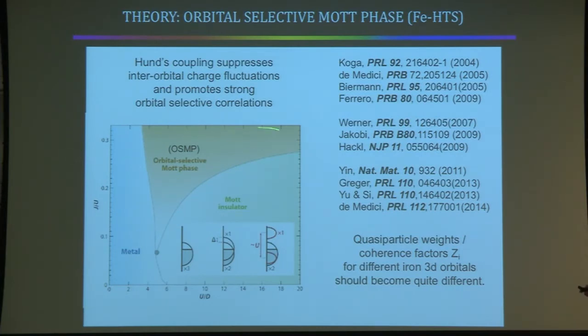That's why this diagram here of orbital selective Mott phases depends on the strength of the Hubbard term on site, but it also depends on the strength of the Hund's coupling between the orbitals. Yes? Pardon? What is Hund's coupling? So Hund's coupling, you can minimize the free energy of a free, typically d electron atom, like iron, by having the spins in the different orbitals all be aligned in the same direction to make a high spin state.